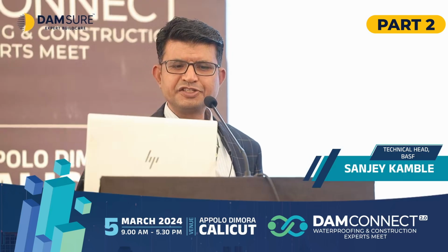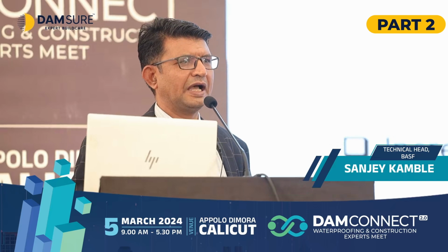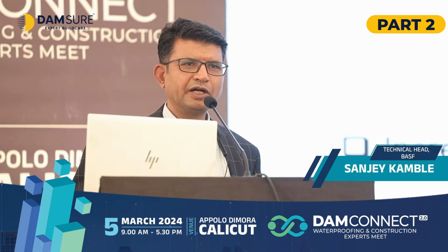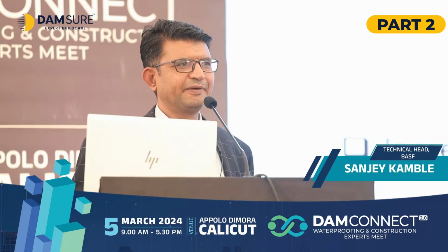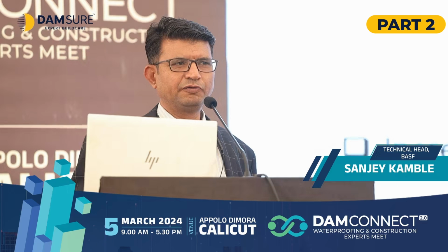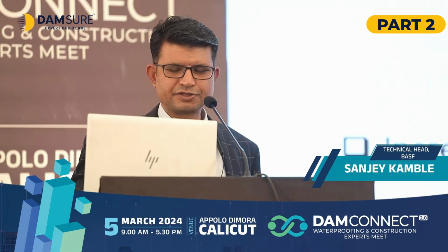The second market trend is that in earlier days we used to have ceramic tiles with higher water absorption, let's say around 15% or above. Now, with the change in trend, these ceramic tiles are being replaced with vitrified tiles, whose water absorption is very low. The vitrified tiles available in the market have water absorption of less than 0.2%.